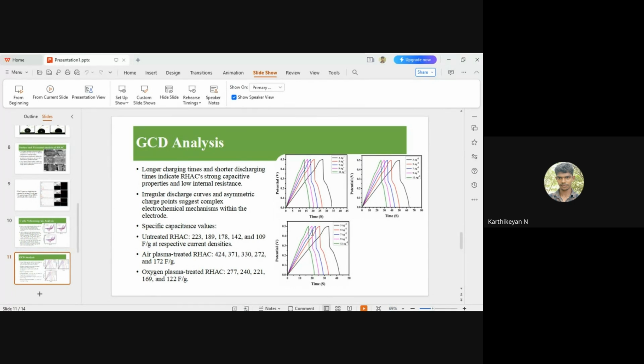The specific capacitance values of untreated RHAC are 223, 189, 178, 142 and 109 F/g at the respective current densities. For air plasma treated RHAC they are 424, 371, 330, 272 and 172 F/g, and for oxygen plasma treated RHAC 277, 240, 221, 169 and 120 F/g at the respective current densities.